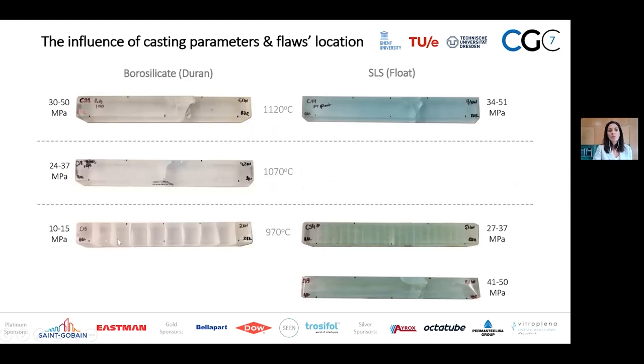But look how dramatically the strength will drop in the lower casting temperatures in these specific fused samples, where actually the crystalline interlayers were exposed to the zone of the maximum tensile stress. But it's interesting to see that the same crystalline interlayers that were interfering so much with the strength were doing absolutely nothing to the strength when they were situated in the middle, so in the bulk of the material.